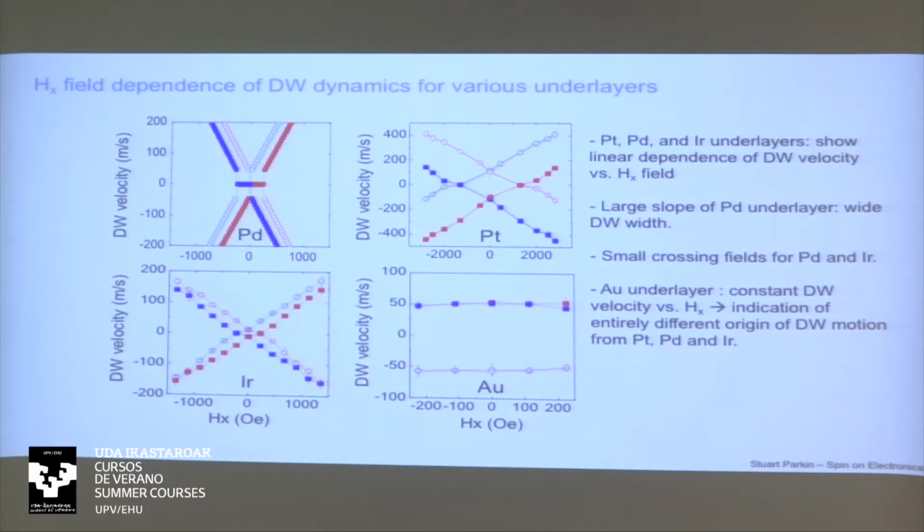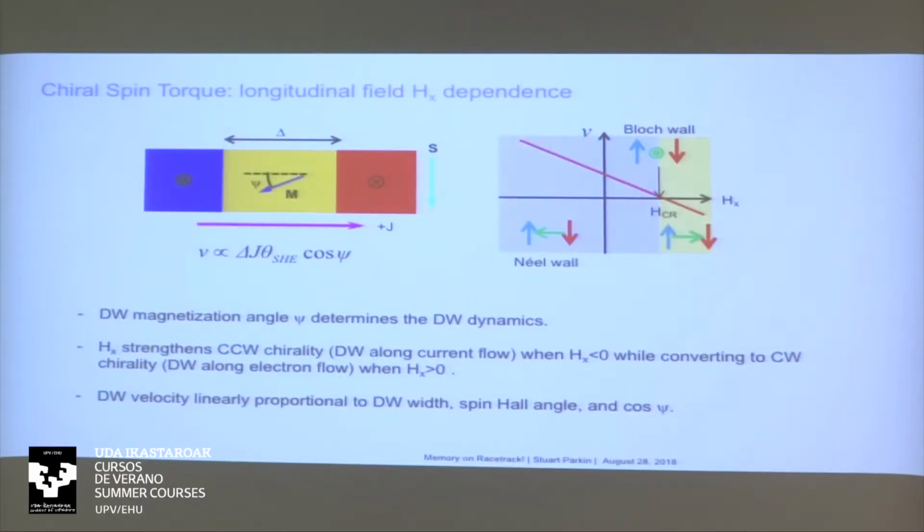It's totally, totally different. And so you end up with this very interesting phase diagram that as we increase this longitudinal field along the wire, you essentially change even the nature of the Néel wall. You can change its chirality, and then the velocity of this wall will change, go through zero at this magical field, but then go in the opposite direction for bigger fields, because it looks like a different type of Dzyaloshinskii-Moriya exchange. This is how we know it's all working.